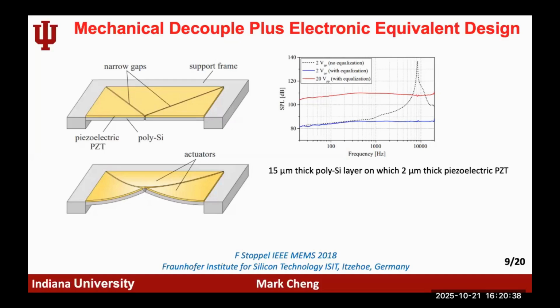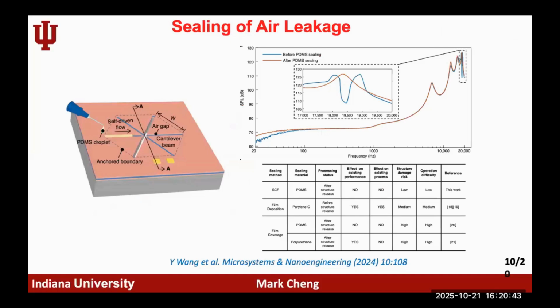So if you cut an air vent in the structure, there's always the question of what the air vent is doing. There are a couple of recent papers that try to seal those vents using polymers such as PDMS, Kapton, and others. For this paper specifically, they put a PDMS drop along the edges, and this capillary sealing finally seals the structure. The improvement you can see is that at low frequency there is a little bit of an increase from the blue line to the orange line. At higher frequency it's not very clear how much you can tell with those kinds of sealing structures.